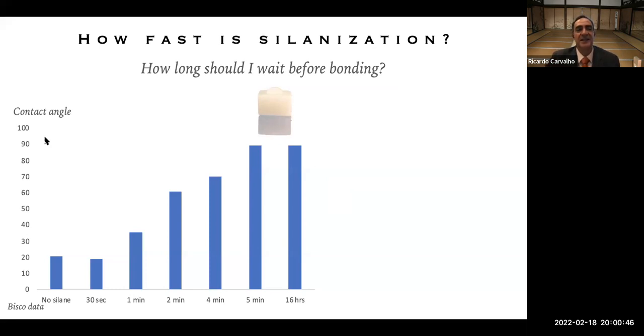As I mentioned before, by utilizing contact angle, I can trace how well the chemical reaction on the surface is happening. The higher the contact angle, the more hydrophobic the surface, and therefore the more effective the silanization. We did this study when I used to work for the company Bisco, and we measured the contact angle after we applied the silane. On the flat ceramic surface without silane, the contact angle with water was 20. Then I applied silane and waited for 30 seconds and measured the angle. There was no change at all, because 30 seconds is likely too short a time for the silanization reaction to occur.